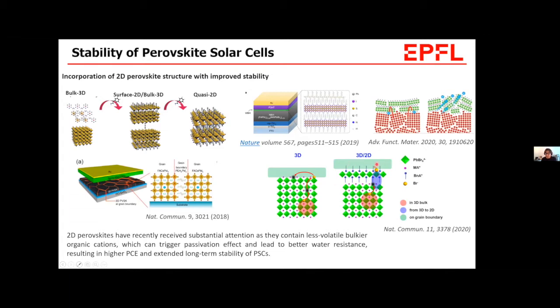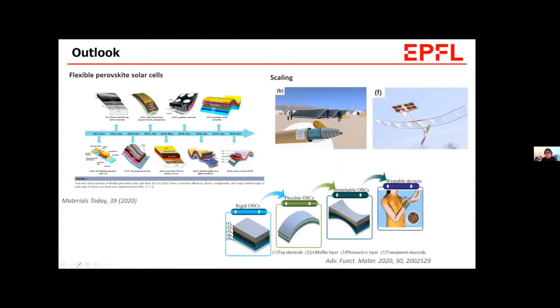But with this 2D passivation layer, the ions should overcome the higher barrier energy to get through the organic capping in this 2D perovskite region. So this kind of ion migration suppression is important to make the perovskite solar cells, well, of course, as well as LEDs stable.